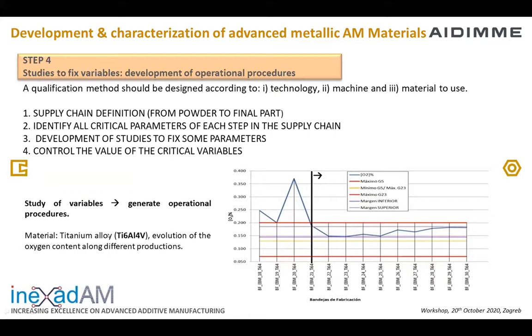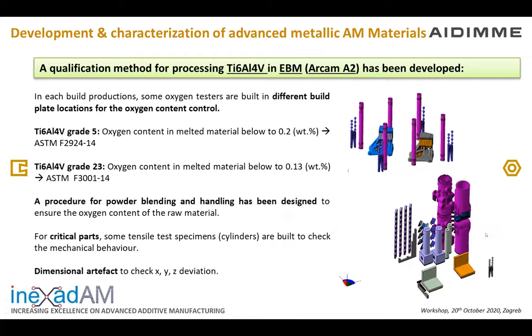For example, for titanium alloy, we have learned that it's mandatory to control the evolution of the oxygen content along the different productions. You can see here different productions, and we need to keep the blue line, which is the oxygen control, between the red lines, which are the control limits.